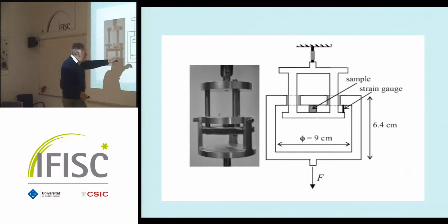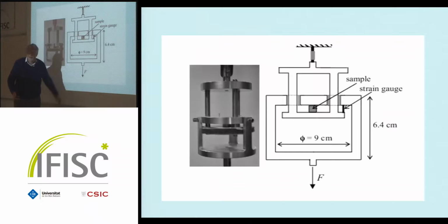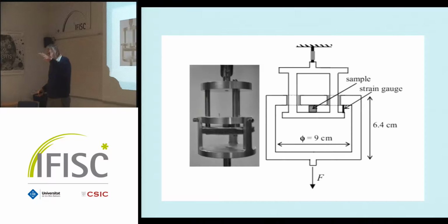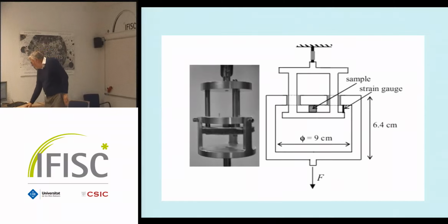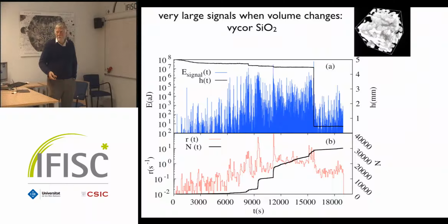So what you do here is you have a very slowly increasing force, which gives you a stress on your sample, and then you measure how the sample collapses, or what the sample is doing. So here is this high-tech nano-porous Vycor. It's basically SiO2. It has a porosity of about 40%. You can make different Vycors, and it's used for filling of aircraft wings inside. You need light material, which is quite stiff, and we want to destroy it.